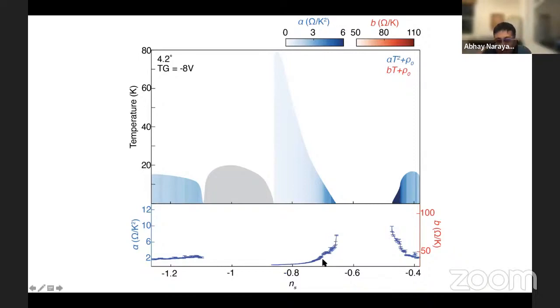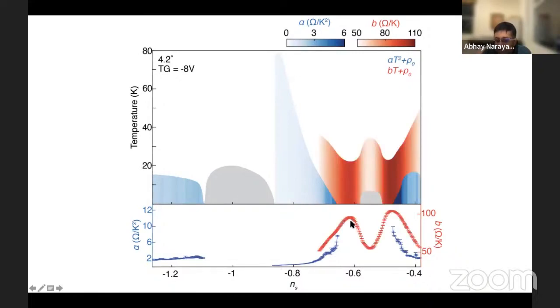And corresponding to that, if I look at the coefficient of the T-linear behavior, it is maximized at the quantum critical point. And just in terms of numbers, interestingly enough, this number is comparable to the so-called Planckian bound, where the scattering rate is given in terms of temperature.